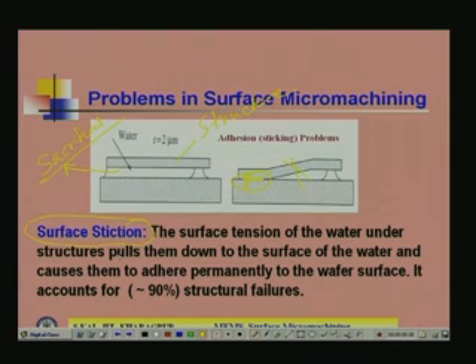The surface tension of the water under the structures pulls them down to the surface of the wafer and causes them to adhere permanently to the wafer surface. It accounts for 90% of structural failure. That is the major problem of surface micromachining. There are certain solutions also in order to get rid of that kind of surface stiction.